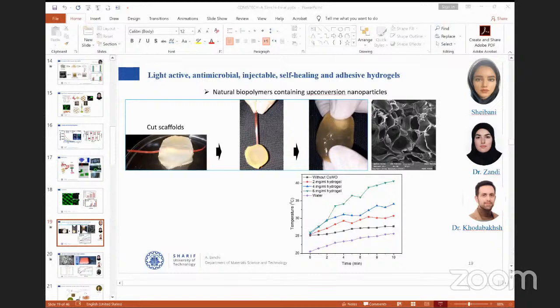So the gel has self-healing properties and very adhesive properties. And then we use light. We irradiated light to the system with a wavelength of 800 nanometers. And we measured the surface temperature of the gel. You see the temperature of the surface depends on how many nanoparticles are added to the system. The temperature increased and killed bacteria. This is unpublished, very recent work of our group, as a development of the previous work.